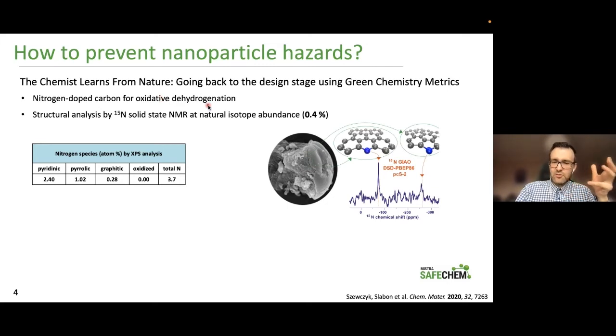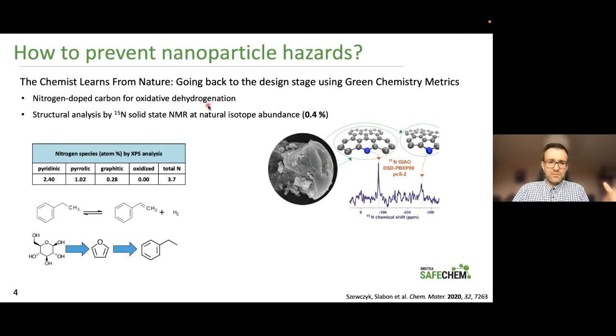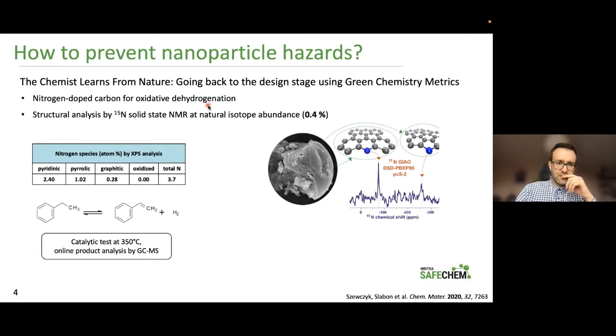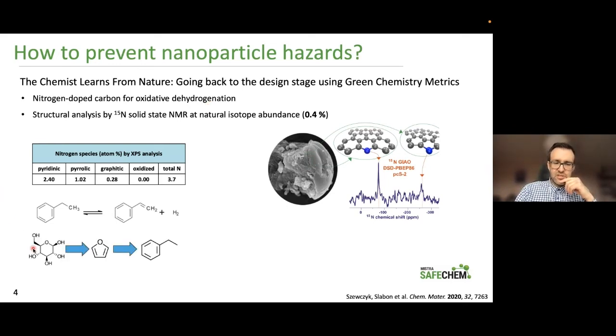And this is quite interesting from the green chemist's perspective, because if you think about plastics like polystyrene, you're using crude oil, as I have shown you. But what if we take wood, we separate cellulose, we then go to sugars. From sugars, you can go to furans, you can then get ethylbenzene. And if you then dehydrogenate the ethylbenzene, you can get to styrene, green styrene, and after polymerization, you have green polystyrene made out of trees, actually.